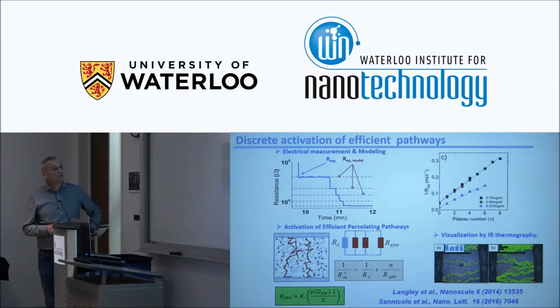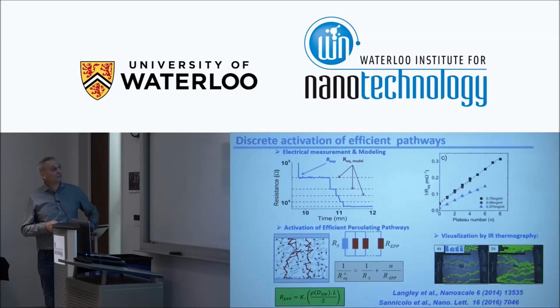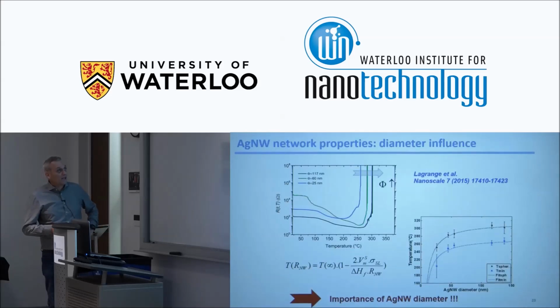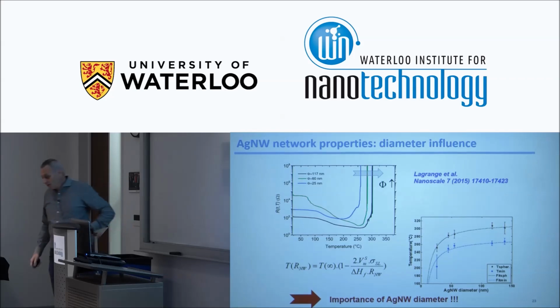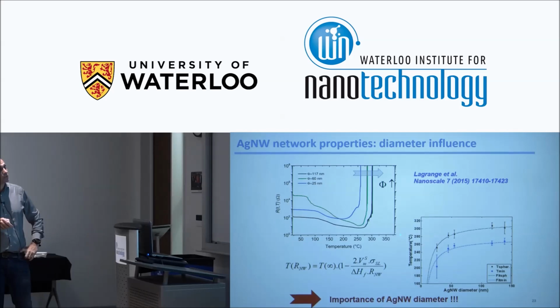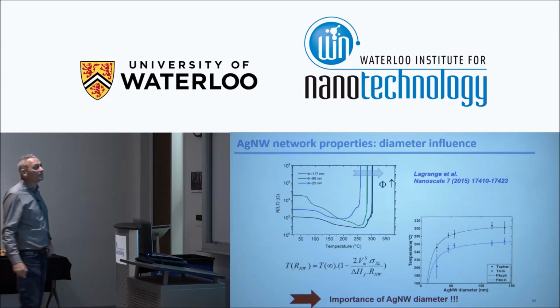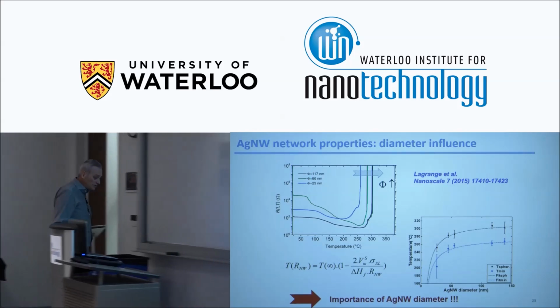So that was a rather non-expected observation, for sure. And the point is that we also studied the effect of the morphology, the sizes of the nanowires. For example, that's an example of the diameter influence on the properties. Again, this is the log of the resistance versus temperature during thermal treatment, a thermal ramp. And exactly what I've shown before on denser networks, so we don't see that much discontinuous decrease here. But with different average diameters of 25, 60, and 117 nanometers.